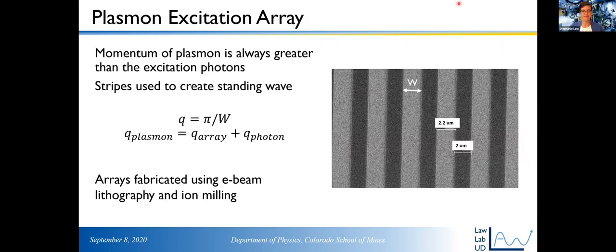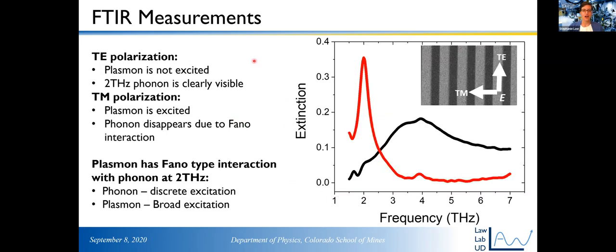That's where we're going. Okay, so, I said all of this already. Yeah, so the momentum of the plasmon is always greater than the photon, so we're going to etch it into these stripes. This is just an SEM of the stripes that we've made. Again, it's a standing wave resonance, so the wave vector is just pi over the stripe width. It's a standing wave resonance. And we do Fourier transform infrared spectroscopy measurements to actually measure the optical properties.